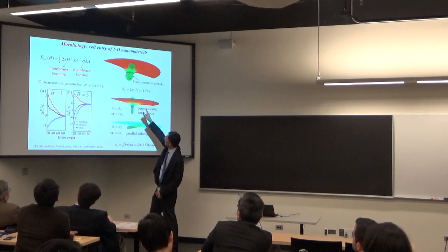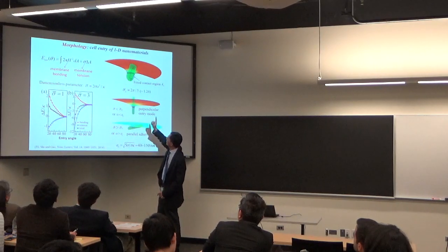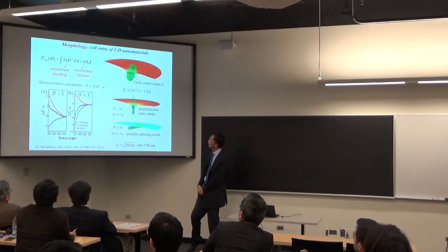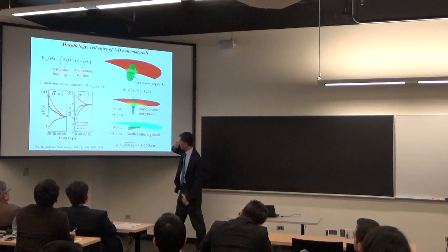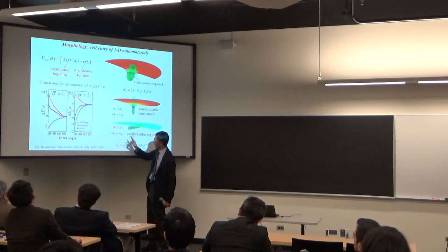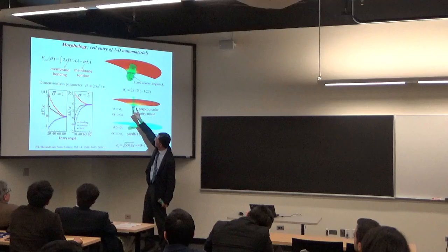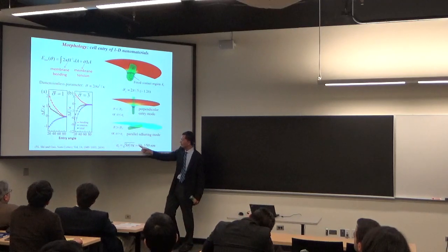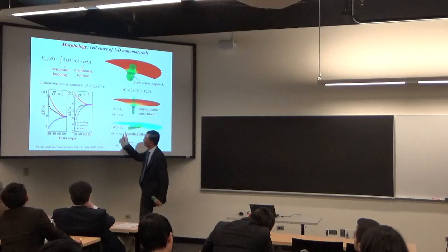So there exists a critical value of this non-dimensional parameter, given by 2 pi over 5, sigma c. If this non-dimensional number is smaller than this critical value, the fiber will go into the cell in a perpendicular way, normal to the cell surface. If it is bigger than the critical value, 2 pi over 5, then the fiber will go parallel to the membrane surface. And this critical number can also be interpreted as a critical size for the nanomaterial. So sigma equal to sigma c can be interpreted as A equal to A c, the size of the fiber, about 5 sigma pi kappa. It's about 40 to 100 nanometers, so about 100 nanometers, a nanoscale dimension.